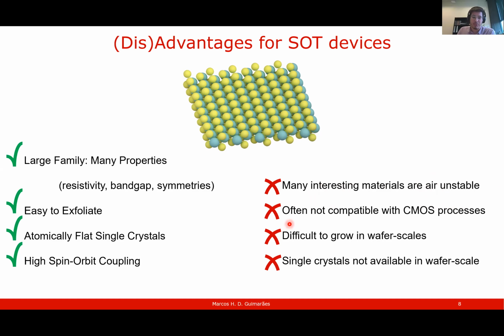The growth and the processing is often not compatible with CMOS processes, but there's a lot of effort in this direction. I won't go into details, but we are getting closer and closer to that. It's pretty difficult to grow in wafer scales, but again, there are many groups doing an excellent job over there. And the single crystals are not available in a wafer scale yet. So for this reason, we use mostly exfoliated materials because, well, we are experimental physicists in the lab. We just want a proof of principle, so that is good enough.